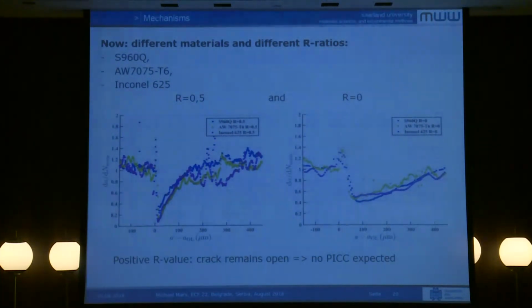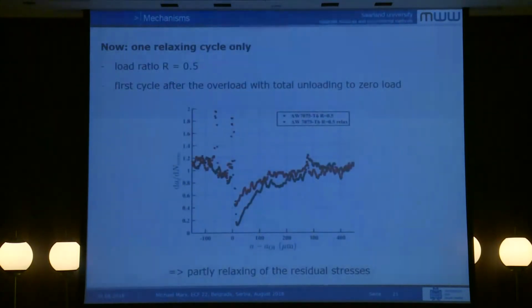And what's very interesting, maybe as a last result, if you compare different loading ratios, 0.5 and 0, you will find that with 0.5 as loading ratio, you have a stronger deceleration of your crack propagation rate than with the load ratio of R equals 0. And if you make an experiment with just one unloading, so you have here the diagram for the R ratio of 0.5, and this is also for an R ratio of 0.5, but just one cycle with an unloading down to 0 load, then you will get a completely different behavior. So just one relaxation means that you get a completely different behavior.